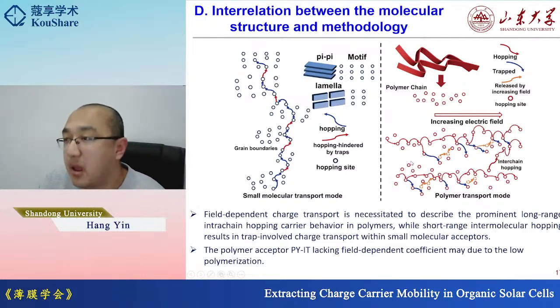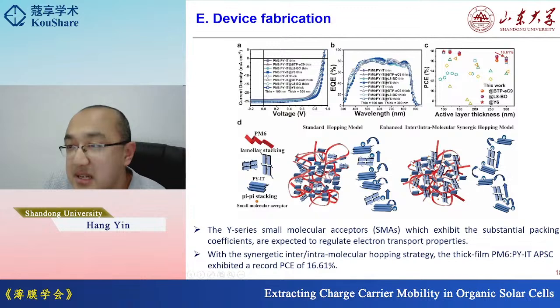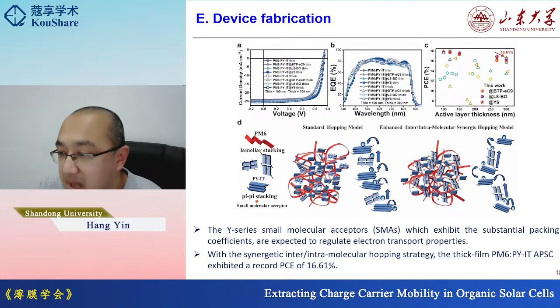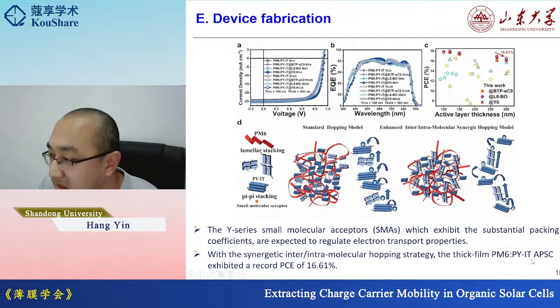And finally, based on all the analyses above, we just make some solar cells to confirm whether there are some real applications. And we observe with the synergetic intramolecular hopping strategy, we fabricate the thick film PM6:PYIT based all-polymer solar cells, and with a very high efficiency. We can see here the 16.6. I think the efficiency is desirable.